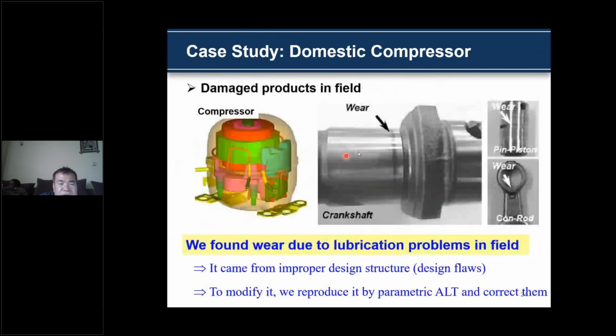This is a damaged product in the field. We found a lot of wear on the surface of the crankshaft due to a lubrication problem in the field. It came from improper design of the structure. To modify it, we reproduce it with parameter ALT and collect the data.